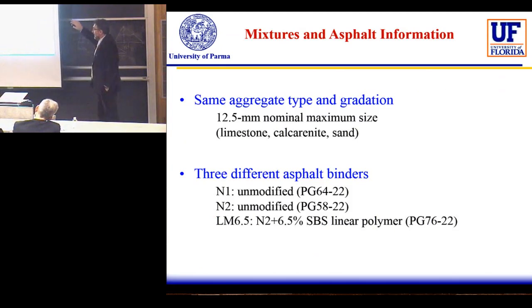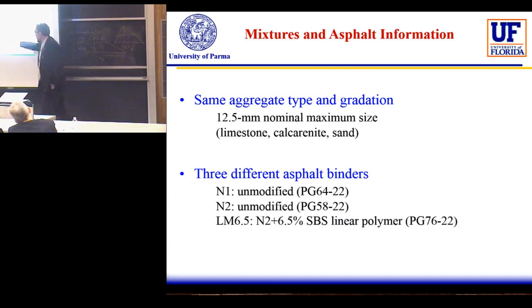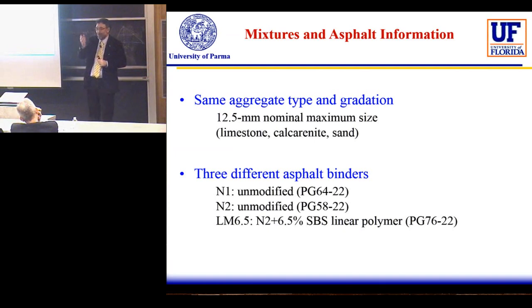This was the information about the material. Same aggregate type and gradation, limestone and calcareous sand with 12.5 millimeter nominal maximum size, and 3 different asphalt binders: 2 different unmodified bitumens, and a 6.5% SBS linear polymer modified bitumen, using as a base one of the 2 unmodified bitumens. Why 2 unmodified, the so-called natural? Because the bitumens are strongly dependent on the crude oil that is the origin of the bitumen. Probably you never considered that bitumen is the big recycling operation in the world, because to produce gasoline, the residual part of the refinery plant is the bitumen.